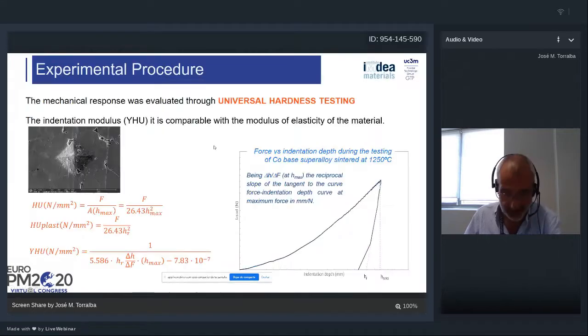Here we have one scheme about how we have developed the universal hardness. We have measured the indentation peak load of each sample, and also the maximum indentation depth, and the plastic deformation depth that we have after one indentation. We can calculate this universal hardness by this formula, in which we introduce these parameters.